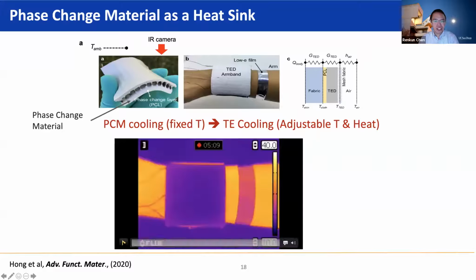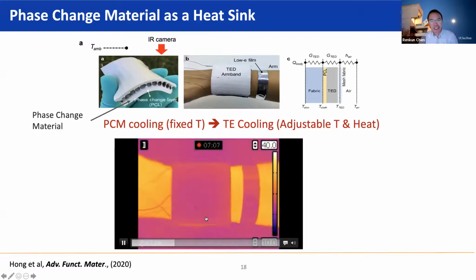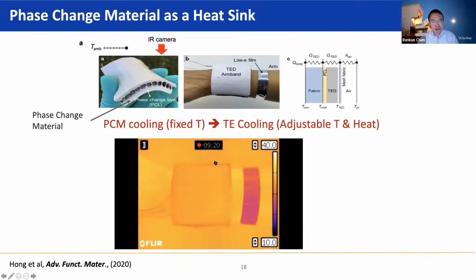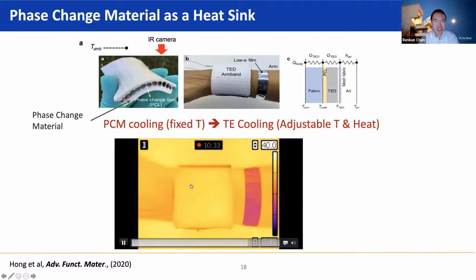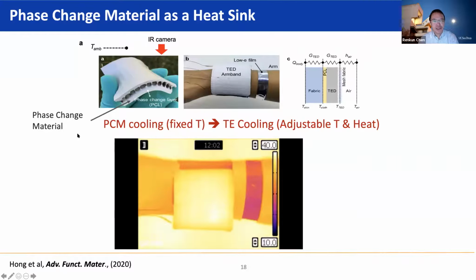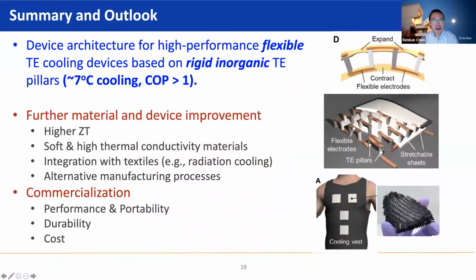So as you can see here, we put this device on the arm, and the ambient temperature actually changes over a wide range, from 20 to over 30 degrees Celsius. But the device can actually keep the same temperature regardless of the ambient temperature, with a phase change material. So that shows the flexibility offered by the thermoelectric cooling and heating.